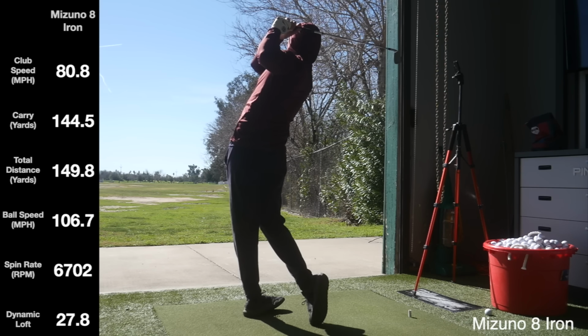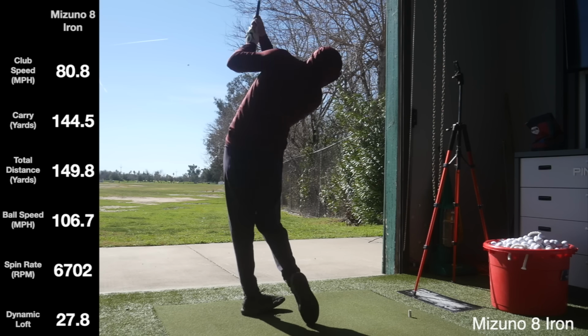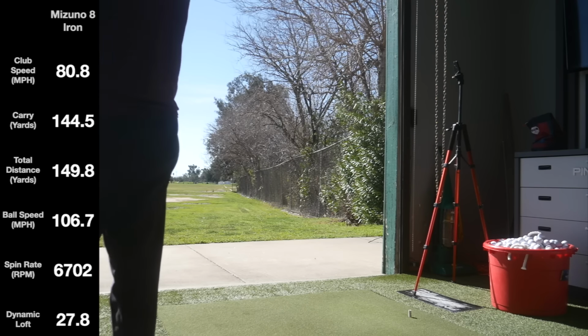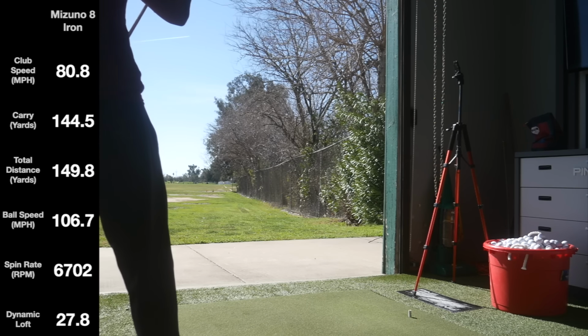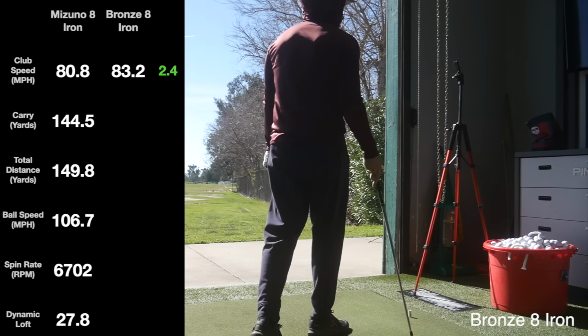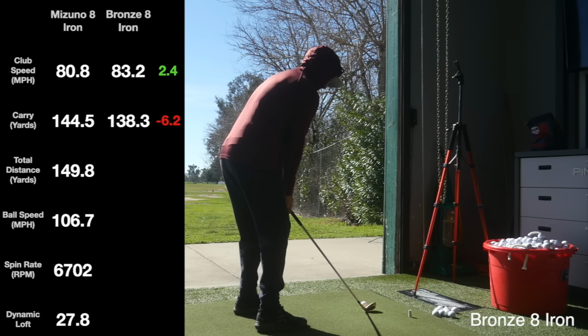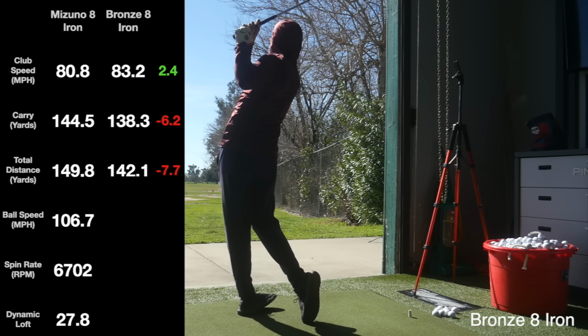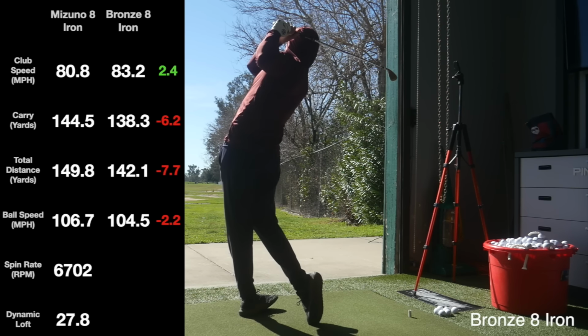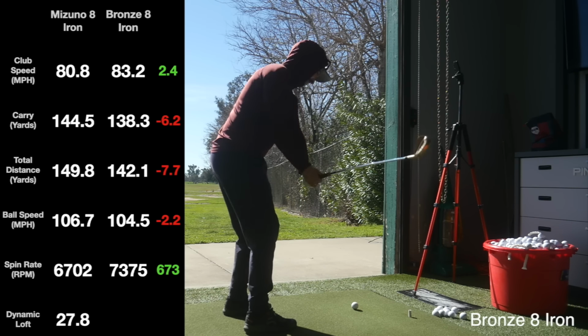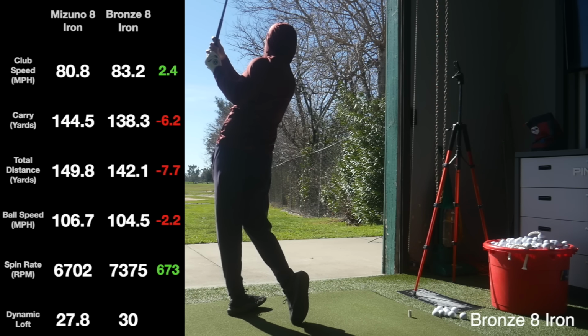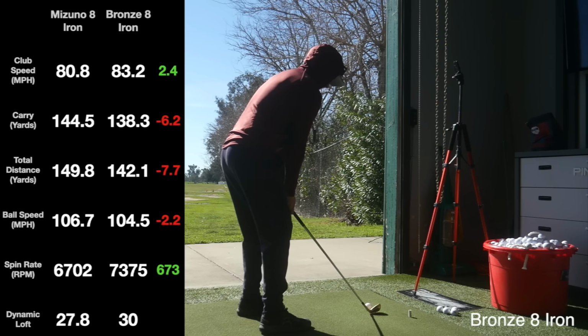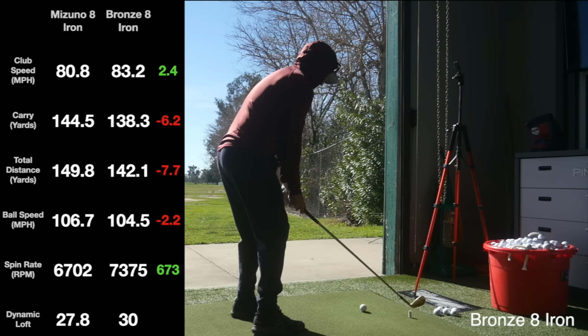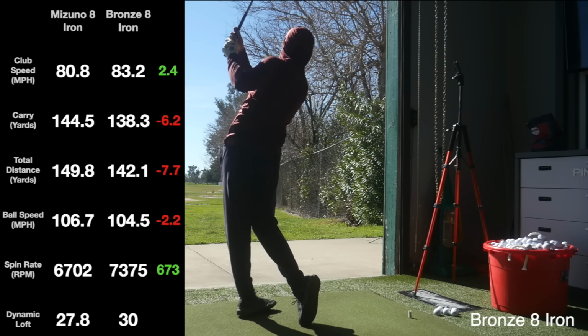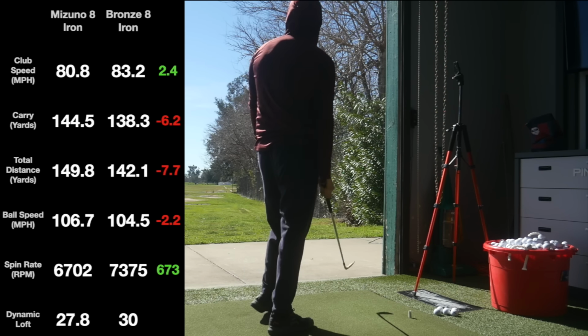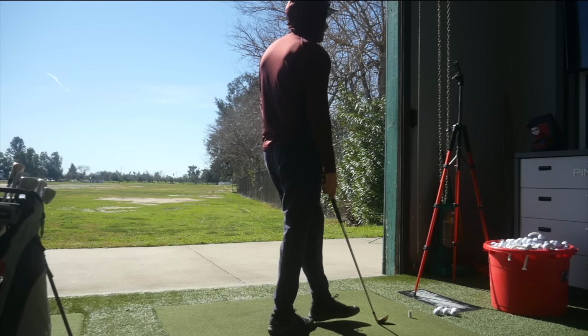I included dynamic loft in here, which is the angle of the club face at impact, which is a pretty important metric for this test. Switched over to the bronze 8 iron, and the first thing to notice is that my swing speed is up 2.4 miles an hour, which is due to the lighter head weight. But my carry is down 6 yards, distance is down 7.7, ball speed is down 2 miles an hour, spin rate is up 673, and that's probably mostly due to the 2.2 degree increase in dynamic loft versus the Mizunos, but the spin rate might also be attributed partly to the difference in steel versus bronze, given that softer metals can add a slight increase on spin rate.